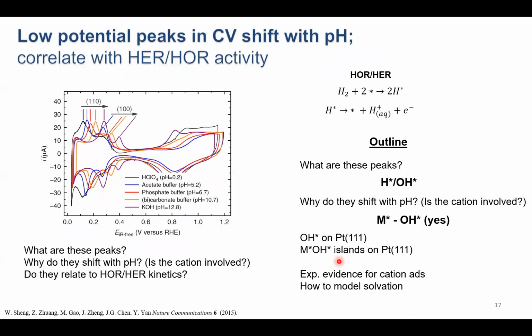To give you an outline for the rest of the talk, as well as some spoilers, we will show that these peaks correspond to an exchange between adsorbed hydrogen and adsorbed hydroxide and water on these platinum step sites. We'll show that they shift with pH due to the close approach of a cation, an alkali metal cation, to the electrode surface, which then interacts with adsorbed OH and water along the step. We'll then show that we can extend this same concept to explain the effects of pH on hydroxide adsorption on flat platinum surfaces, not just on steps.